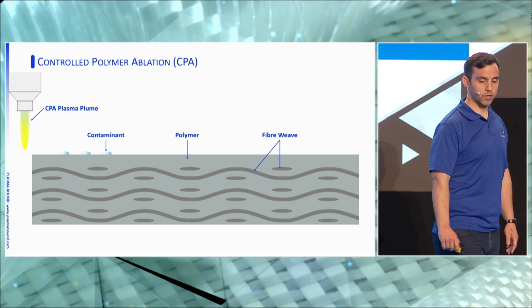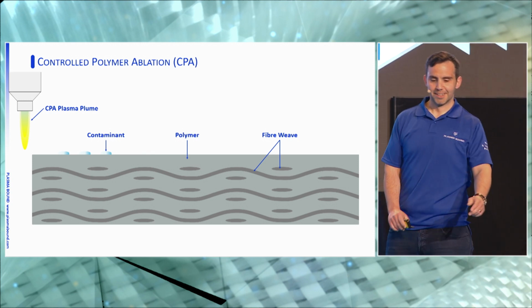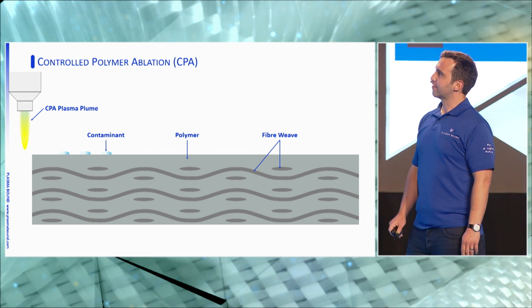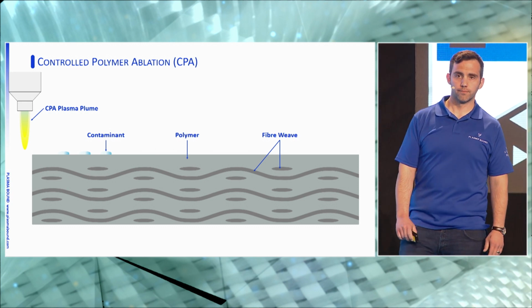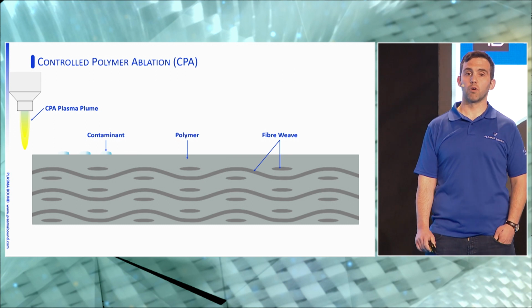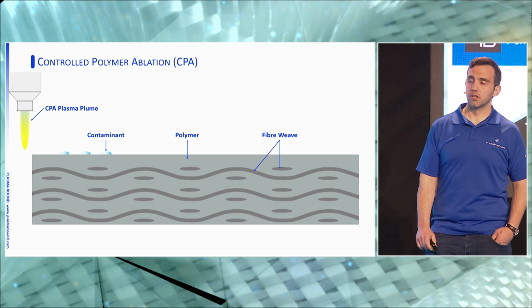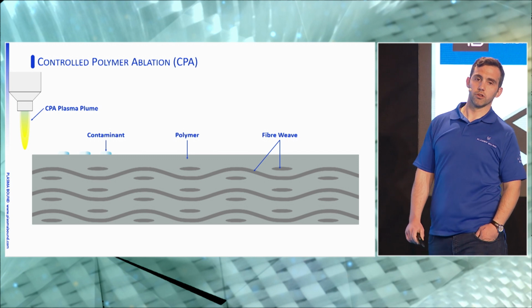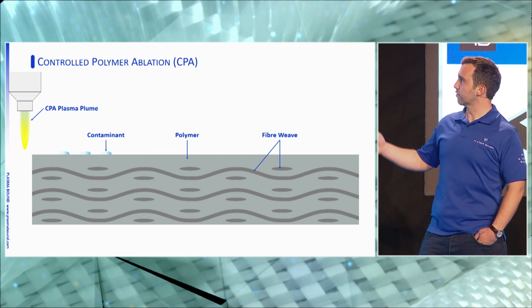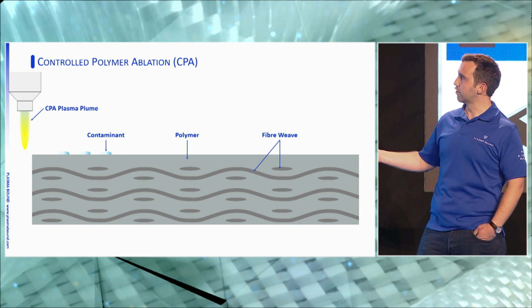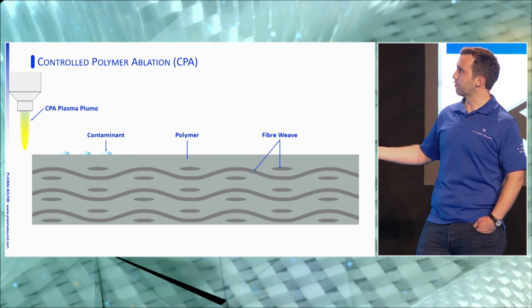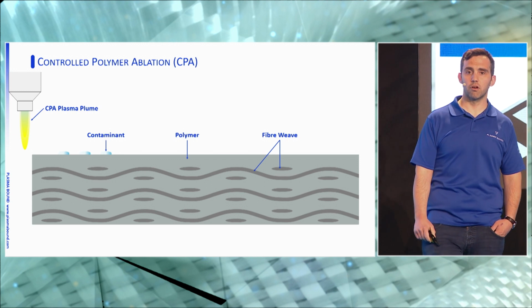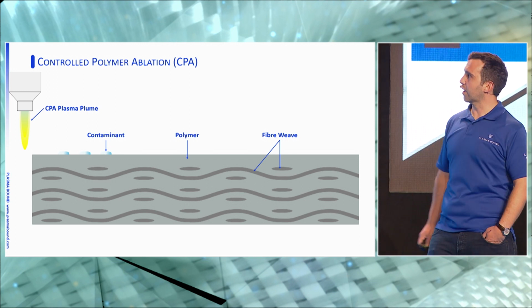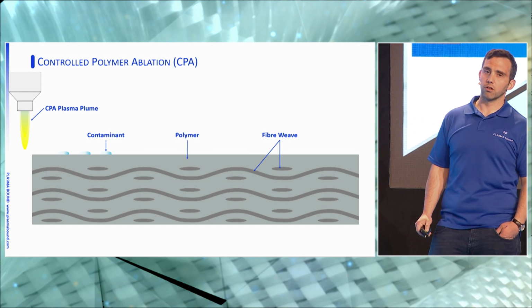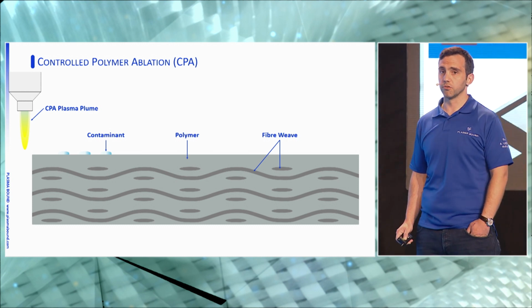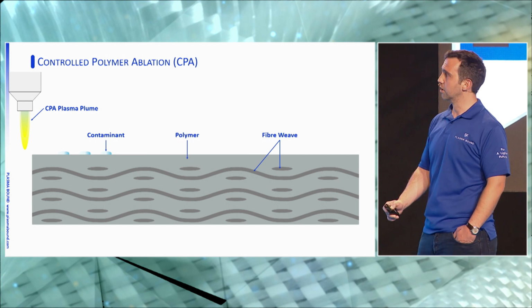Now, onto the reason why Xavier, my commercial director, wants me to talk today. CPA is the technology we've developed. We're a spin out of University College Dublin, but this is what we are essentially selling. This technology does away with all of the previous issues that were discussed. We've discussed the weak polymer layer, which is this material here. We've discussed contaminants getting in the way, and we've discussed the fact that the fibrous weave is the strength of a composite. If you can do exactly what the roughening and also peel ply are trying to do, but without causing any damage to the fiber structure or any potential contamination, that would be ideal.